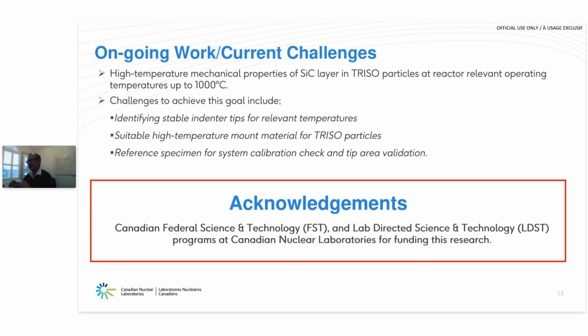Right now we are using high temperature cement, which we notice, at around 500 degrees C or above, starts to disintegrate. So we need a more suitable material to mount these TRISO particles, to prepare and subsequently test. And the third one, last but may not be actually last, is the reference sample, which we can actually use for the system calibration check and the tip area validation itself.